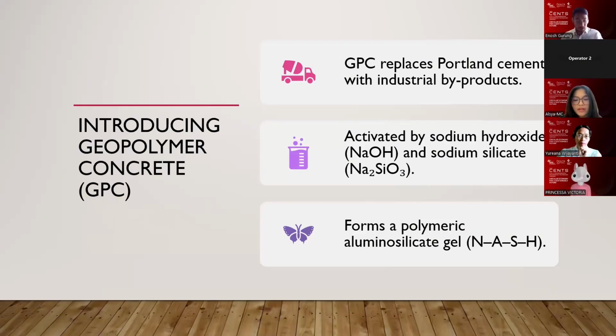Geopolymer concrete avoids the clinker entirely. It uses fly ash, slag, and other aluminosilicate sources activated by sodium hydroxide and sodium silicate. The reaction forms an N-A-S-H gel that binds the aggregate together. Next slide, please.